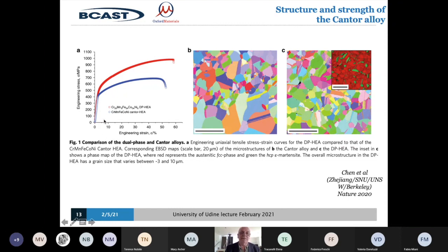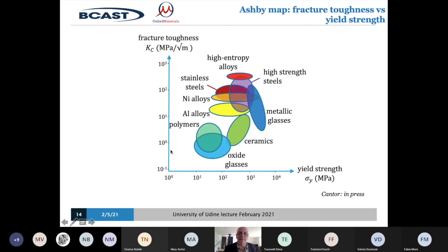Metals, pure copper, pure gold, pure nickel, are soft. They don't go very high up here, and then they deform a lot. That's why you can beat gold into gold leaf and turn almost pure iron into those beautiful cars that I showed you. The Cantor alloy has an amazing mixture of, my pointer stopped there. There we go. It has a tremendous mix of both high strength, it goes up to high levels on this axis, and ability to deform. It deforms the best part of 50 to 100%, but at the same time it has strengths up into the half a gigapascal to a gigapascal level. This is shown more in this so-called Ashby map, which is the same sort of thing really. On the bottom axis you've got the strength, and on the upper axis you've got the fracture.